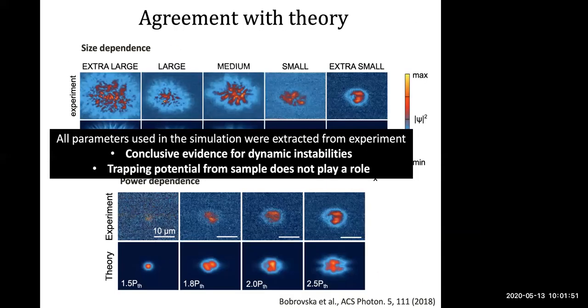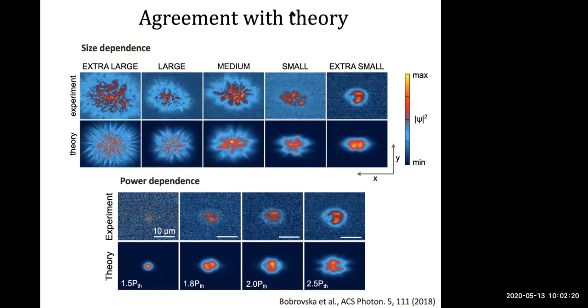So yeah, that's a very good question. In principle, we should see some signature of this in terms of K-space broadening. It was not really dominant in the K-space data. One potential reason is that most of the K-space data we acquire is averaged over multiple shots. If you average over multiple shots, these features will be completely washed out, because for every laser shot the instabilities will give you a different spatial pattern.